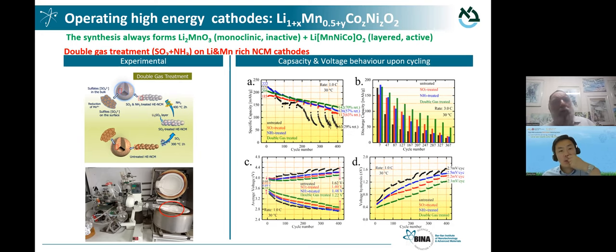So we have an excess of lithium and manganese, and whenever we do the synthesis, and remember, the last synthesis is always high temperature calcination, so we have segregation of two phases. We have one phase is lithium MnO3, the monoclinic inactive at low voltage, with an active classical layer compound, which has usually a rhombohedral structure. And now the key issue here is the surface. Doping is not that important because anyway we have segregation, and the dopant will go to the grain boundaries.